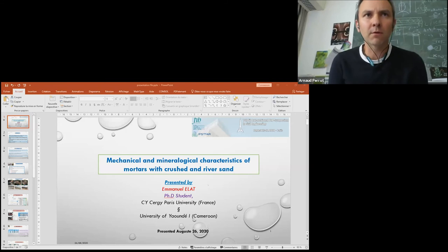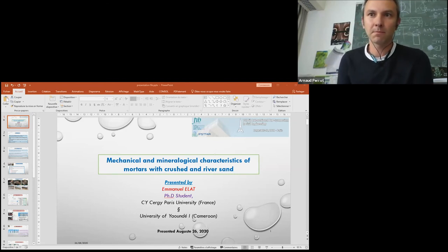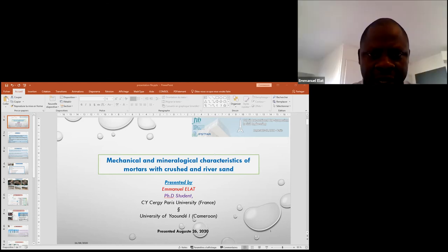Yeah, but when we make standard mortar in France or in Europe, we have a river sand which is quite clean, and there is no problem of porosity with such sand. That's why I'm quite surprised. That's why I said in the context that there are some river sands that are very poor in thin particles. So in this work we wanted to recommend that when river sand doesn't have a sufficient quantity of thin particles, it will have a consequence on the physical and mechanical properties and porosity.